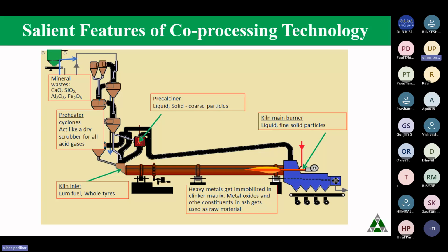Whatever material we put into the cement kiln, the organic material gets completely combusted, and the inorganic material becomes raw material in cement manufacture. You may have some chlorine, some sulfur, some nitrogen in the waste material. They will get oxidized. Chlorine will probably become HCl. Sulfur will become sulfuric acid or sulfurous acid. Nitrogen will become nitrogen oxide. Phosphorus will become phosphoric acid or phosphorous acid. Fluorine will probably become hydrogen fluoride.